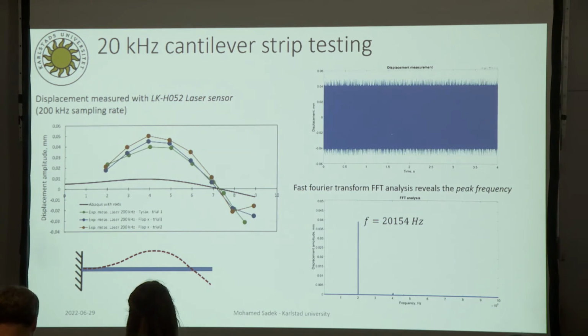We do not know exactly why this discrepancy exists. We have some ideas. It's still under investigation. We have a couple of ideas on where to look. We think that other modes might come in and superimpose the amplitude and increase it in that way. We're not sure which mode. There are several candidates, several modes that are close to 20 kHz. That could be a reason for that. We will continue to investigate it. But as of right now, we do not know the reason for this difference here.